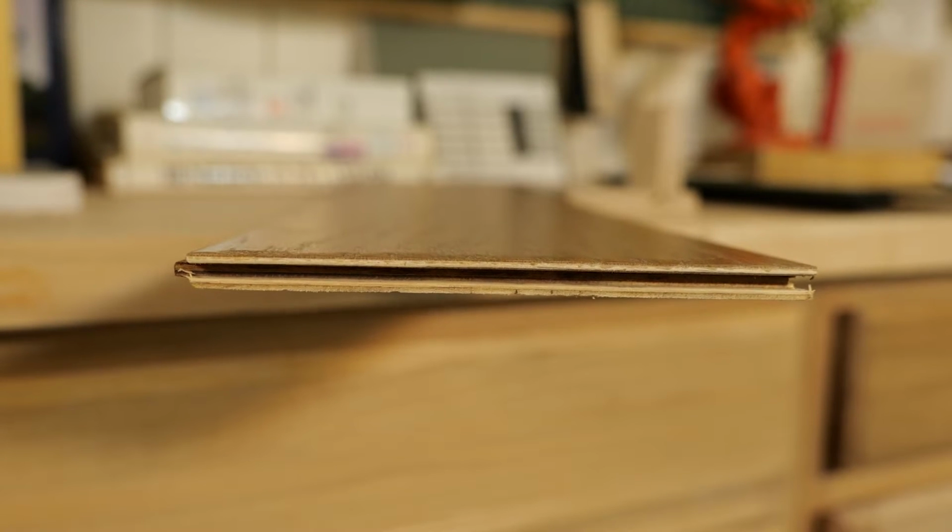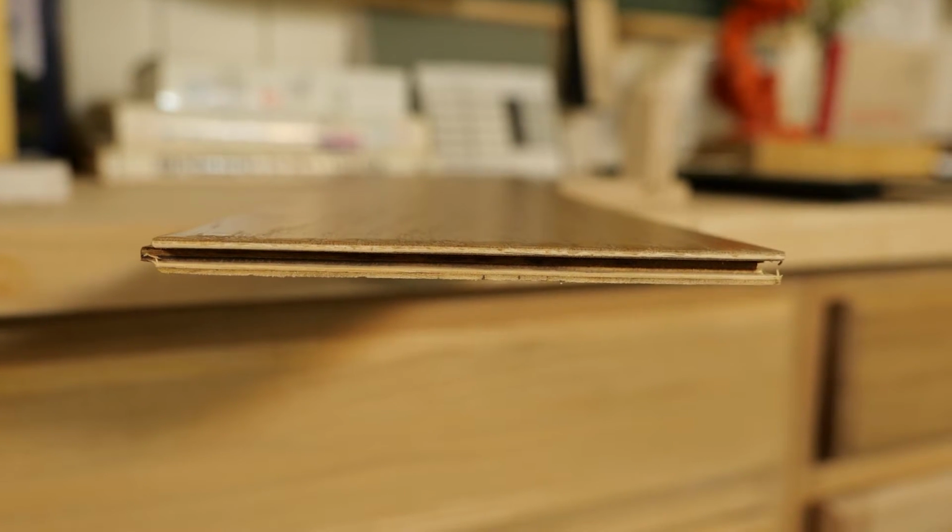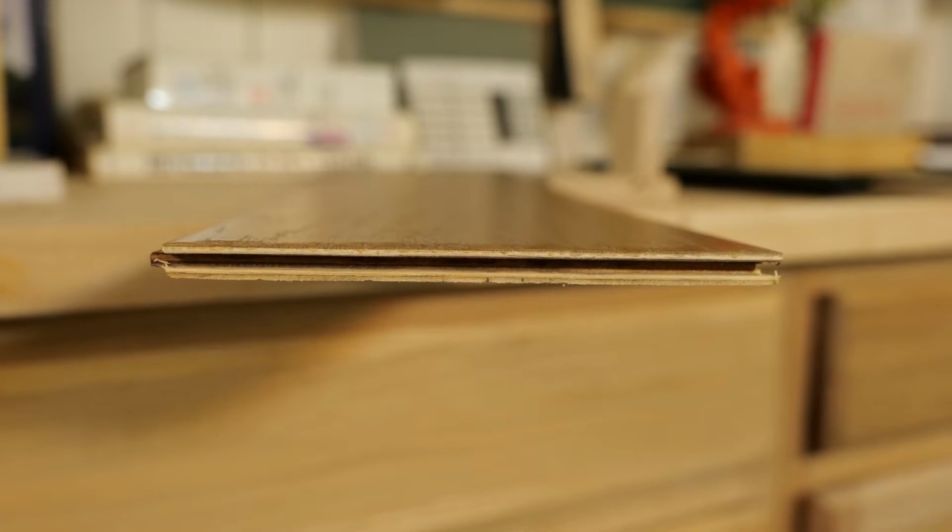So this is, again, oak, but it's just incredibly thin. We're maybe 20 thousandths worth of a top veneer, which is really thin. Nothing necessarily wrong with that. It definitely makes the floor cheaper, but what it does is now this oak is so thin, it's not able to act like oak. It is not able to withstand the force of the screwdriver. All of those forces transfer straight through the oak into the substrate, and in this case, this is a poplar plywood substrate. So that's very, very soft. Remember I said that's about 500 on the Janka hardness scale.